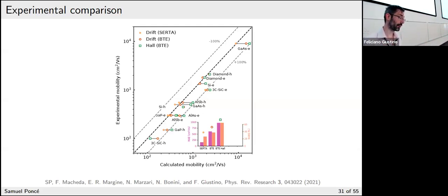And the other thing that, to me, is still surprising is that effective masses in DFT are sometimes not very well described. And this is something that people don't look at so much, in my opinion. So we still have some issues in some materials in some directions. And so we also looked at correcting the effective mass by using the experimental one. And that typically brings you also a bit closer to experiment. So if you have some experimental information, you can try to tune back a bit. If you have partial information on your materials, let's say you don't have the mobility, but you have this quantity, then you can expect to improve your estimation a little bit.